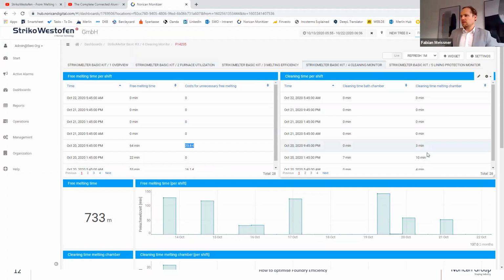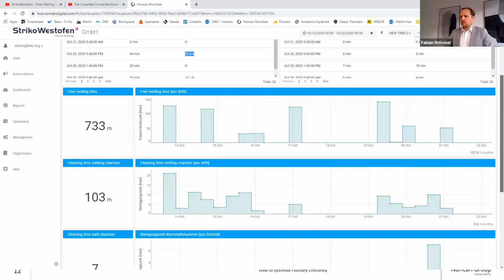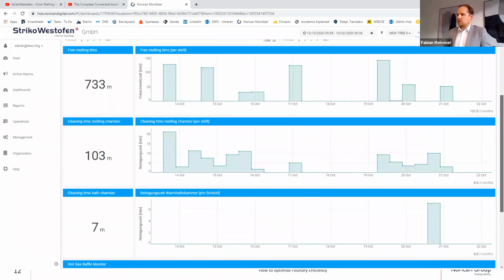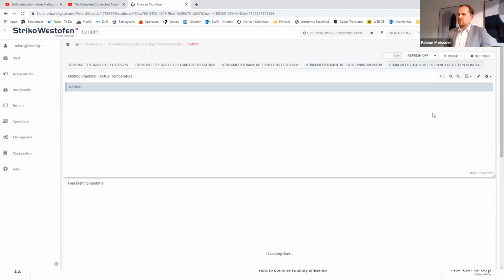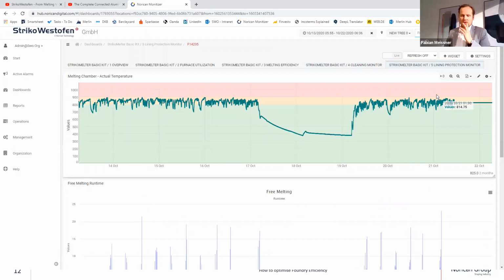You can see the cleaning times per shift. So how much time was the holding chamber cleaned? How much time was the melting chamber cleaned? So you can monitor what else. You can see a lot of data, which for example, here you can see the temperature in the melting chamber. We normally say if you go above 900 degrees, you have a high risk of damaging your refractory. So this is a red zone. If you are between 800 and 900, it's not optimal. We would rather recommend to stay below that in the melting chamber. But this helps you to see how the furnace is run at what temperatures over time, and so on.